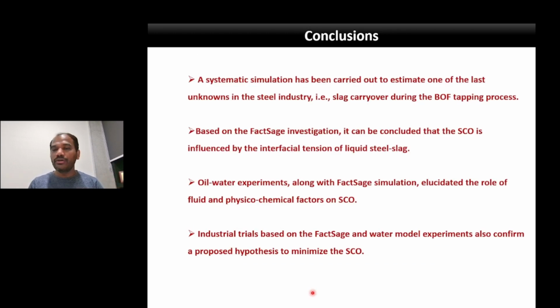So I would like to conclude here. We have conducted this very systematically using the FactSage simulation to understand the slag carryover process. And we understand that based on the FactSage investigation, the slag carryover is actually influenced by interfacial tensions of the liquid steel and the slag, and water model experiments have also confirmed the same thing. And based on all these understandings, we went to the industry trials to confirm that there is a strategy to control the slag carryover by slag engineering.